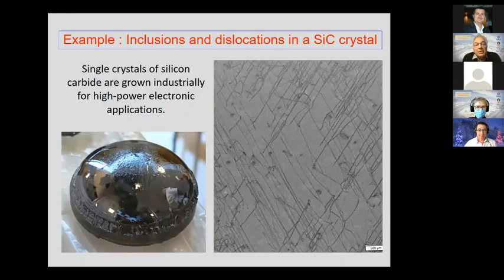The first example is the one of inclusions and dislocations in silicon carbide crystals. Crystals of silicon carbide are grown industrially for high power electronic applications. The image you see here is 500 microns, and you see a lot of lines and small points. The lines are dislocations, the small points are inclusions.